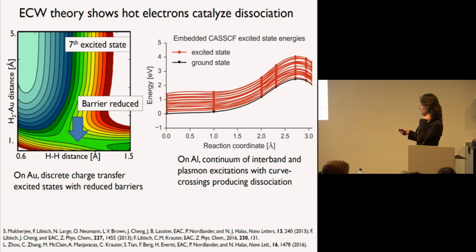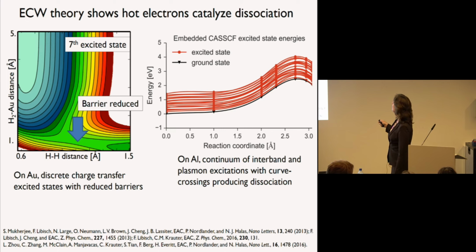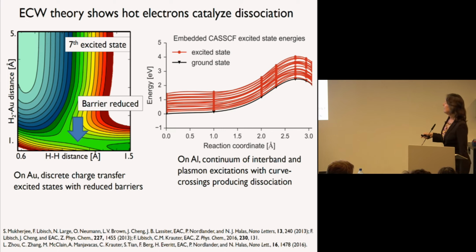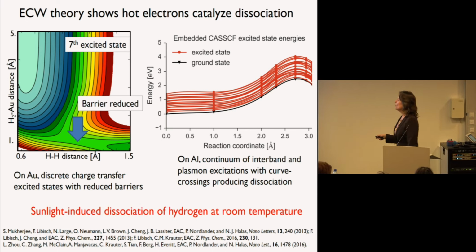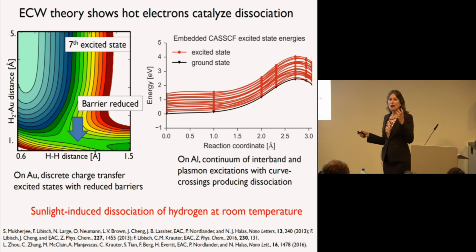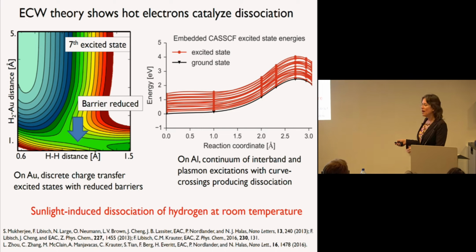So this is a reduced reaction coordinate I'm going to use from now on, because I'm going to be showing you multiple excited states from now on. And this is showing that you have a whole series of states that you can access. And if you get to, this is completely reasonable, a 1.5 eV plasmon, that energy can be converted in such a way to really reduce the barrier if you go across. And because all of these states are basically in continuum, they should be readily accessible. And so basically this shows a way potentially, because these are experiments that were done at room temperature, you can use visible light to dissociate hydrogen at room temperature in this way.